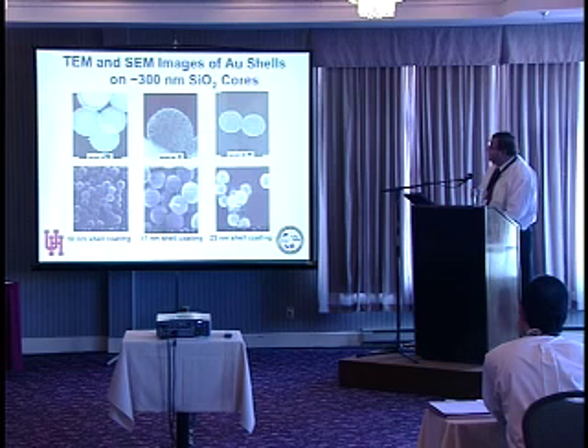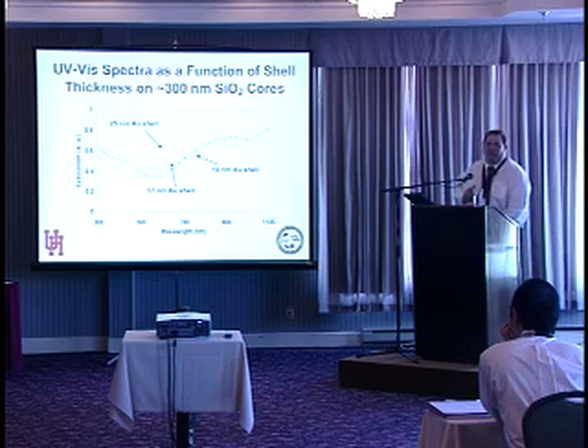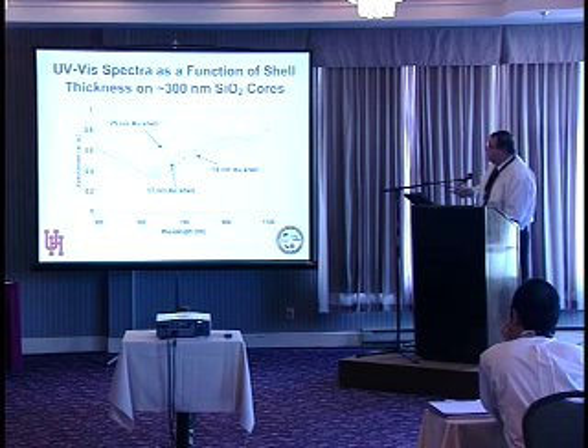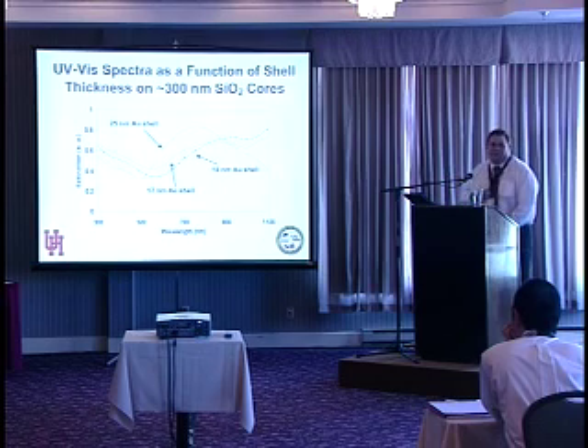Here are, for example, silica core particles that are 300 nanometers in diameter that have gold seeds attached to them. Here are shells grown on these same particles, and you can see the shells in some cases look pretty smooth, sometimes quite rough. We can make shells where the thickness varies from, say, 10 nanometers all the way up to about 25 nanometers. And here are our extinction spectra, that illustrate the optical properties that we could have predicted theoretically for these types of particles. For example, if you have a 25 nanometer shell particle, the absorption here is about 750 nanometers. If you make it thinner to 17, the absorption maximum moves out to around 800, and if you make it 10 nanometers, it moves out to about 900.